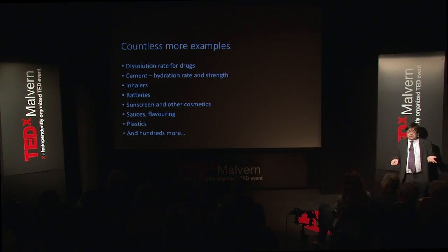For drugs, the finer the particle, the quicker it dissolves. With cement, if it's too fine it sets too hot and you get cracks, but if it's too coarse it's not very strong — again there's that balance between not too fine and not too coarse. It used to be that two percent of the world's energy was spent grinding cement, so over-grinding results in an astronomical electricity bill.